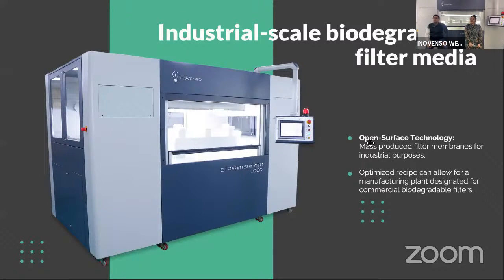Right. So I mentioned before, to try to have a manufacturing line, you need machines like these, basically the open surface technology. I mentioned before that these polymers tend to have clogging issues, especially on most small gauge diameter nozzles or needles. But in the open surface, we actually bypass the clogging issue because you're just placing the solution on the surface. And in our experience, these polymers that we mentioned before work much better on the open surface system than they did with the needle-based system. So it's actually amazing. It's not just that the production rate increased really severely, but it actually ensures a continuous process because there's no clogging going on. Of course it needs to be optimized, and you can have a couple of machines similar to these that can help you set up a manufacturing plant in case you want to commercialize it once you have your ready recipe. So let's move on to the next slide.